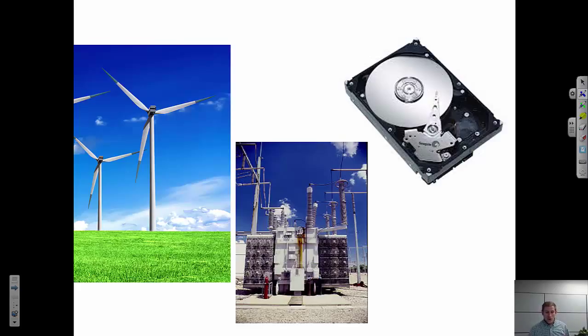Now, really the heart of the matter is that we have different magnets that we'd like to serve different purposes. So a magnet in a generator needs to be a hard permanent magnet. It needs to have some particular magnetic direction, and we want it to stay that way, and we want as much magnetic field as possible coming out of that. A transformer is the absolute opposite. It needs to be magnetic, but it needs to be very soft. It needs to switch its magnetic direction back and forth very readily, because usually we're using these with an alternating current, so the current direction is switching, so we need that magnetic field to switch as well.